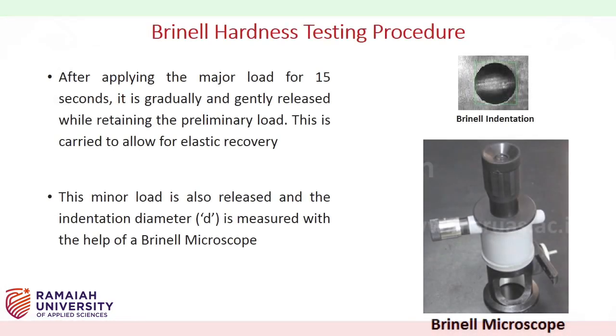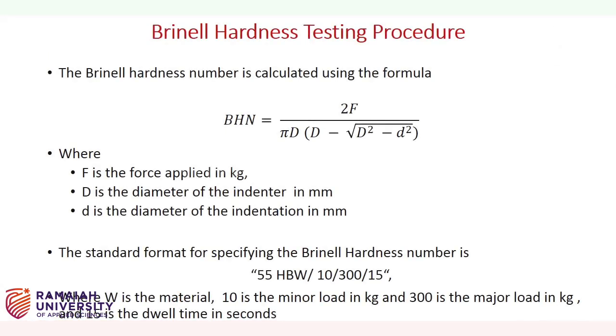After applying the major load for 15 seconds, the major load is gradually and gently released while retaining the preliminary load. This is carried out to allow for elastic recovery. The minor load is also released and the indentation diameter, lowercase d, is measured with the help of a Brinell microscope.